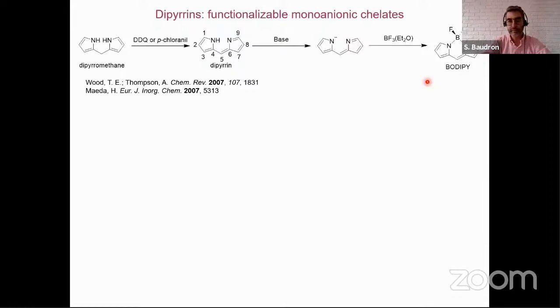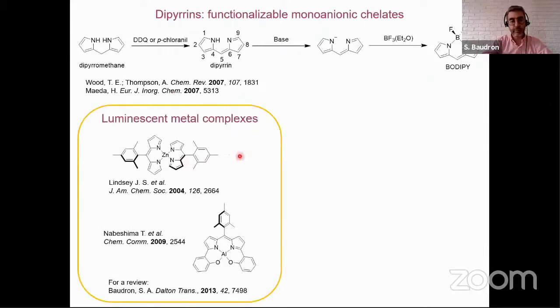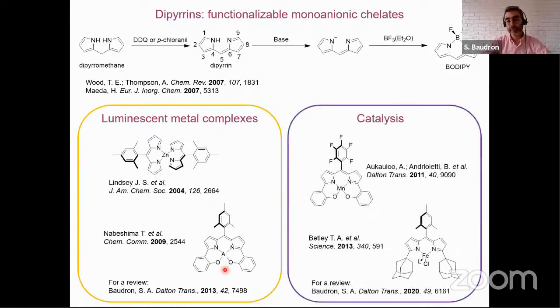When it comes to transition metal complexes, we can find two main applications. The first one is, as for the BODIPY, the investigation of the photophysical properties. So we can show here this homoleptic zinc complex, which has been reported to be luminescent by the group of Jonathan Lindsey, and also playing with a dipyrin backbone and appending two phenol rings. Here can be prepared a sort of salen-type dipyrrin-like ligand, and the group of Nabeshima has shown that these aluminum complexes can be also highly emissive.